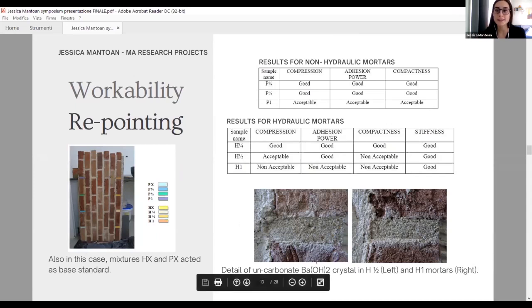A further negative aspect that I found during the study is that after curing, hydraulic mortar containing medium and large quantities of additive left this kind of white stain all around the worked area, and that was a further negative aspect that encouraged me not to use this mortar for my study.